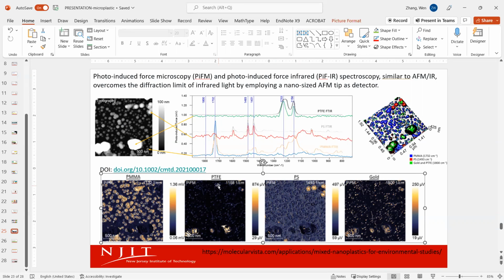So when they are exposed to the IR signal, the sample not merely expands, but also the surface molecules of the polymer matrix shift in polarity, becoming more polarized versus less polarized. So these polarized states will induce strong interactions. It's very complicated. I have no idea how. So the tip and sample would have very complicated polar-to-polar interactions. This kind of force will be recorded by the AFM and then give you a signal here. As long as I see a signal similar to IR over different wave numbers, you're going to generate a so-called spectrum. This signal is not the magnitude of the expansion, but is actually expressed as a photo-induced force in millivolts. So it's pretty much measuring the scattered laser signal.